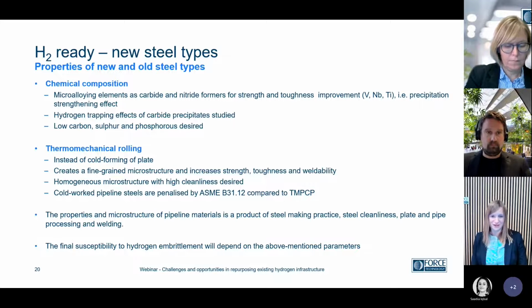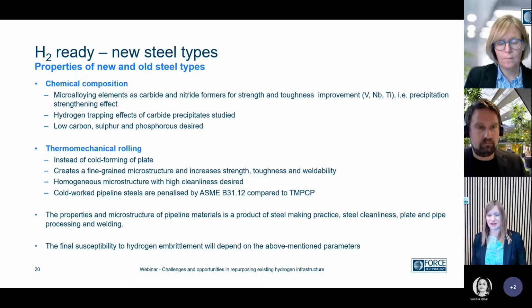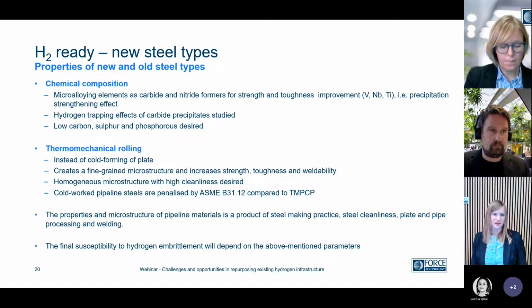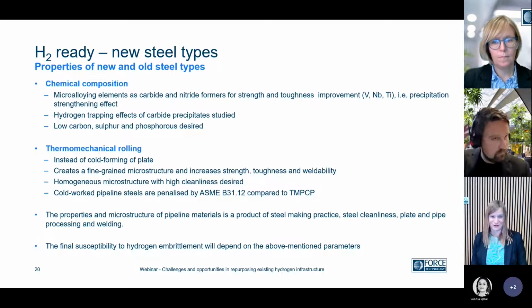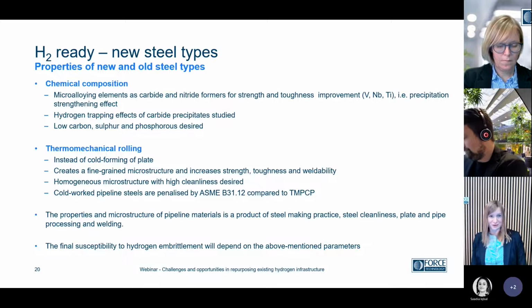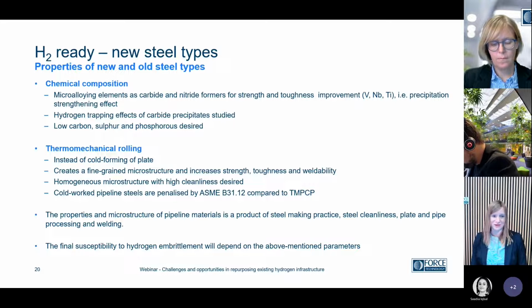accelerating crack growth. But more importantly, the thermomechanical rolling process is widely used. Instead of cold forming a plate, you use an intermediate temperature. It's not a hot rolling, but it creates a fine-grained microstructure, which increases strength, toughness. Toughness is important for hydrogen embrittlement, and weldability. And it introduces a homogeneous microstructure, and often, of course, high cleanliness, low impurity level is desired. But in the end, the final susceptibility to hydrogen embrittlement will depend on a number of parameters.